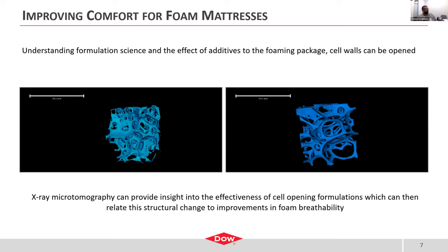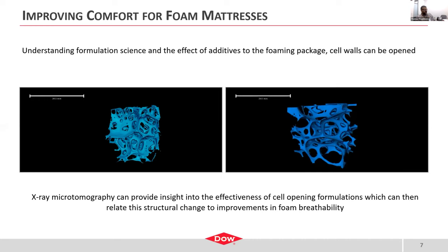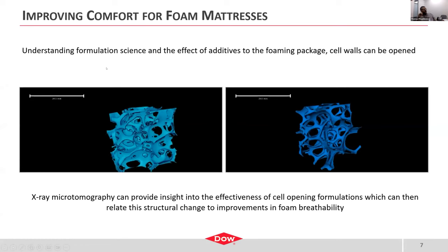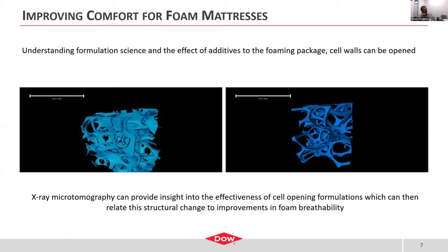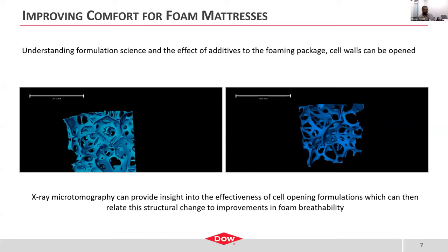And what I'm showing here are two X-ray microtomography scans of polyurethane foams. The one on the left is a traditional polyurethane formulation, and the one on the right is a formulation that has been altered using new chemistries related to surfactant technology. One thing that you can tell that's different about these two materials is the one on the left has a lot more what we call cell walls.